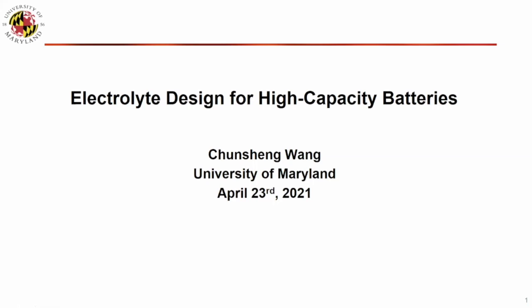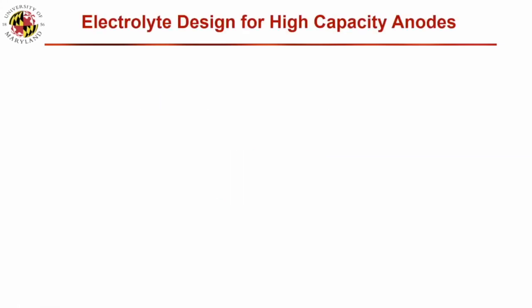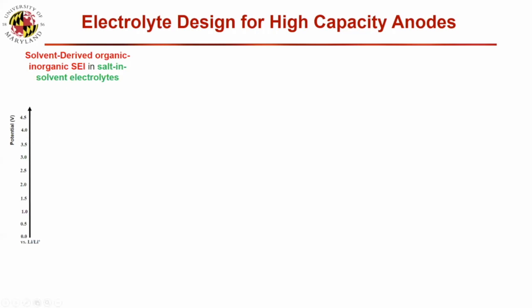Today, I will talk about electrolyte design for high capacity lithium ion batteries. First, I want to mention what the current electrolyte is for the lithium ion battery. This is the electrolyte potential window, referenced to lithium metal. Aqueous electrolytes normally have a 2.0 volt window, because they cannot extend to potentials lower than 2.5 volts versus lithium, where they will generate hydrogen, and above 4.5 volts, they will generate oxygen. The water cannot form a solid phase to passivate the electrode. So that's the limited window.